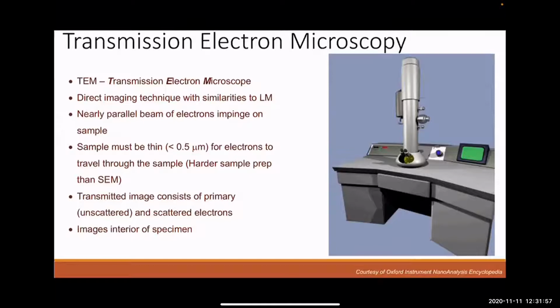So, for example, it could be very simple if you are a researcher that is looking at nanoparticles. Well, they're already really thin. You can just put them onto a TEM sample grid and directly look at them. But if you have a bulk sample, if you're a geologist, you're looking at a rock, or we've got electrical engineers that grow semiconductor structures that are fairly thick, how are you going to look at that? Or if you're a biologist, for example, and you want to look at a cell, how are you going to do that? Because the cell is fairly small, but it's microns to tens of microns, and you need something much, much less than that. And so even half a micron here would be really too thick. A gold standard for a biological specimen would be like 70 nanometers. For materials specimens, that could be smaller still, down to atomic or a couple atomic layers.